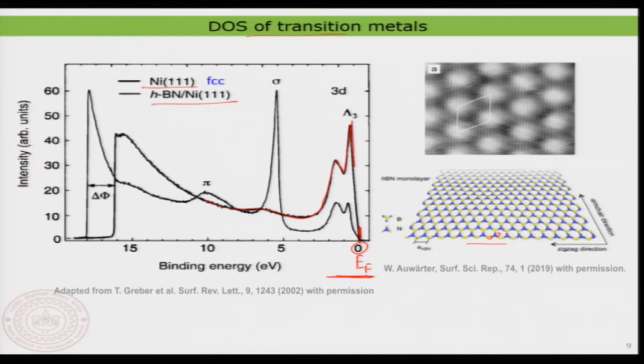But now you deposit this molecule, or prepare this material, on top of the nickel 111 surface, and then you can do the UPS, ultraviolet photoelectron spectroscopy. You clearly see that new features are coming up. Of course, these two features near the Fermi energy are truly coming from the nickel 111 surface itself, because I have told you that whatever we are measuring is just from a few layers near the surface. That means nickel is still visible to the ultraviolet photoelectron spectroscopy, and therefore we see something from that.